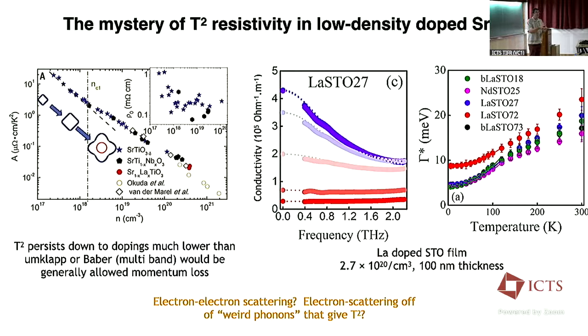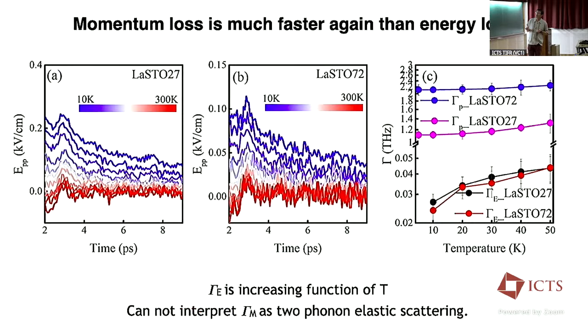One of the possibilities is that the source of the T-squared resistivity is not coming from electron-electron interactions, but it's coming from some kind of, if you will, weird phonons because of the unusual lattice properties of strontium titanate. And I think what we show in our results, and I'll just say it here in words, is that we rule out this scenario as well, because we show that we are in a regime where, again, the energy relaxation